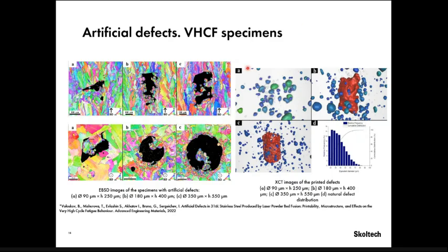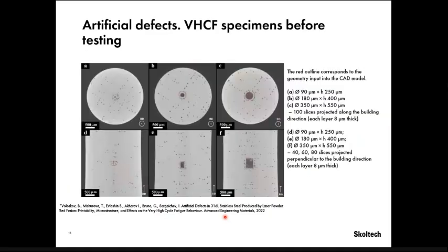in some specimens for very high cycle fatigue, we couldn't observe them in computer tomography. So repeatability here may be not so good for the smallest defect. However, for the relatively large defects, like this one is 180 microns in diameter and 350 microns in diameter, they're quite good and correlate with CAD, as you can see here.